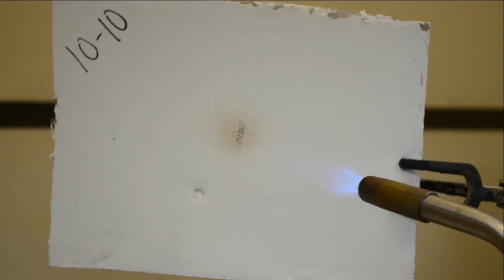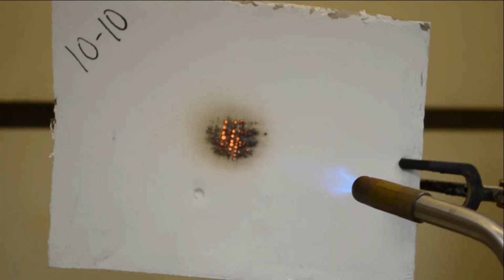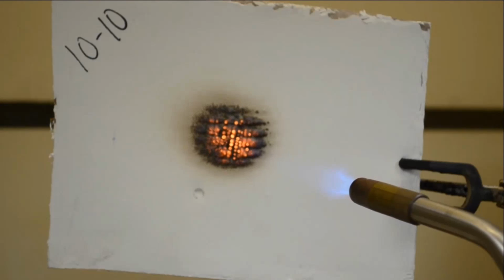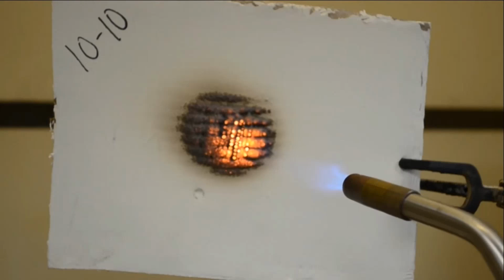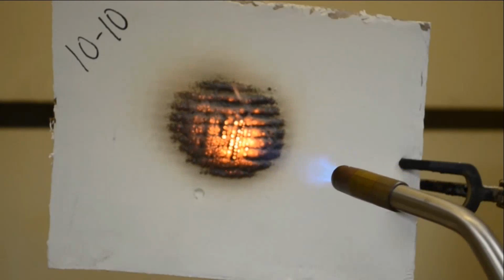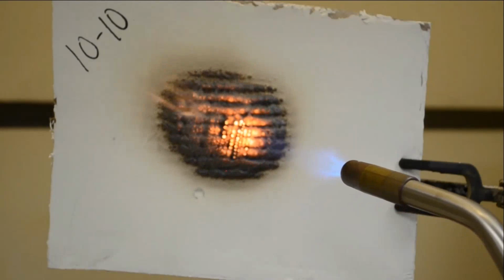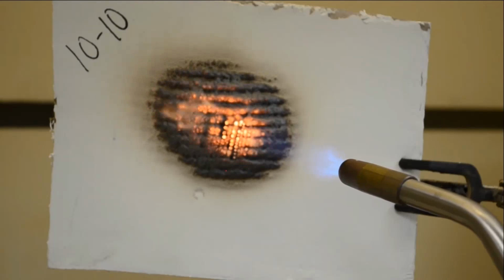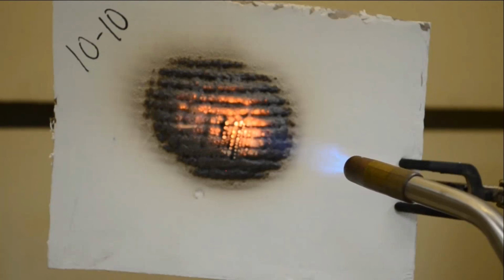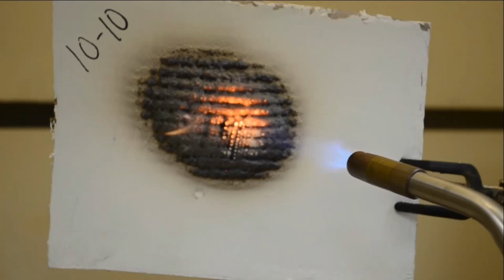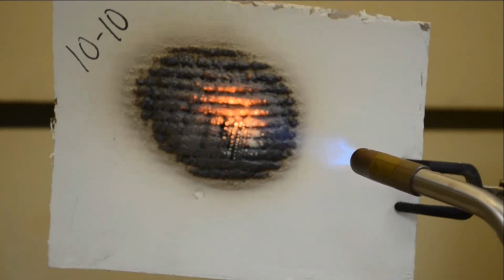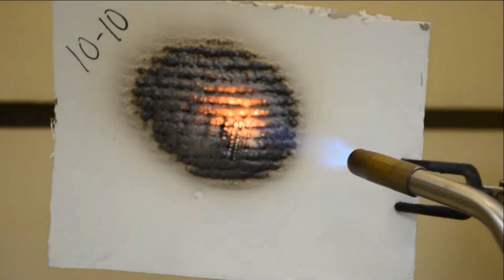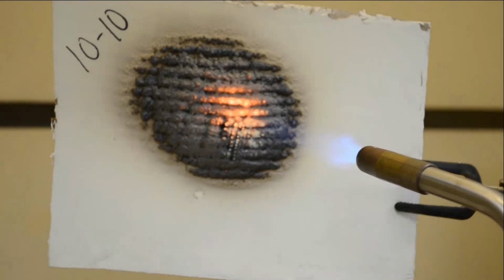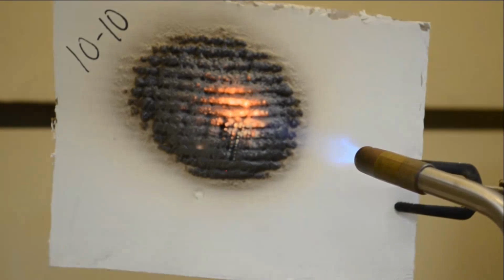This demonstration features standard corrugated cardboard that has been coated with Flame Control 1010. Flame Control 1010 is a solvent-based intumescent coating designed to reduce the spread of flames when subjected to fire. Flame Control 1010 has been tested by UL in accordance with the ASTM E84 test specifications and has been assigned a Class A flame spread rating. 1010 dries to a flat finish and has the appearance of conventional paint. On contact with either a direct flame or excessive heat, 1010 intumesces or puffs up to form a dense protective foam layer that checks the spread of flames and retards heat penetration.